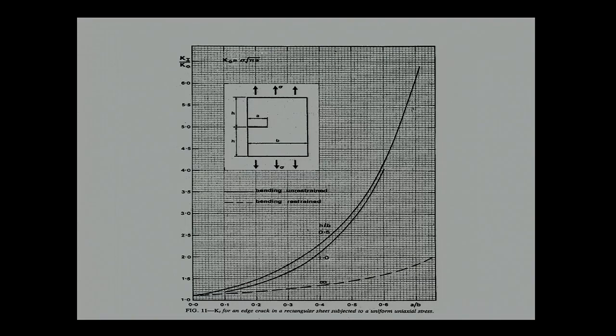How they compensate is to use edge crack to account for the surface. So in this case, he again has a chart showing an edge crack, if you have load applied. In this case, the crack will be a through thickness crack. And how the length versus the width of the plate will have the effect, right? And in this case, they have also two cases. One is whether the bending is unconstrained, that means the plate can bend. Another case is when the bending is restrained, so that you can only go up, not tilting, basically.